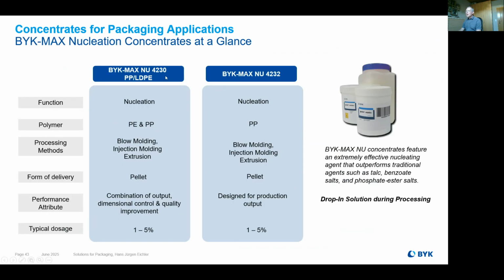We have two grades, I should say. The functionality is, of course, a nucleation. We have this BYK-MAX NU4230 based on a polypropylene or based on an LDPE, depending on your polymer which you're using. The processing methods are quite huge, so it means you can use it for blow molding, injection molding, extrusion. It's based on pellets. Typical dosage is between 1 and 5%, and this 4230 material is just a combination of output and dimension stability and quality improvements.